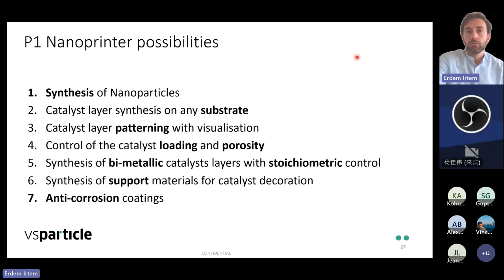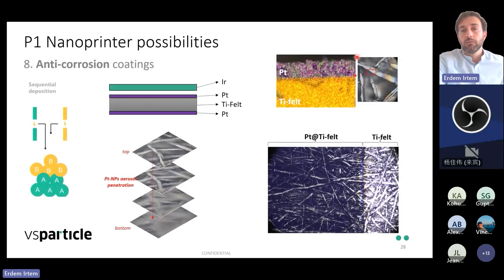Anti-corrosion coatings are also possible, which is lately quite a hot topic for PEM water electrolysis, because titanium undergoes oxidation and corrosion, which decreases the lifetime of the electrolyzer stack in general. So what is usually conducted is that titanium felt is coated with a thin platinum layer, so then you can preserve the electrical conductivity and keep the electrical resistance low for a long time. And with this technique, we already employed this, so we also